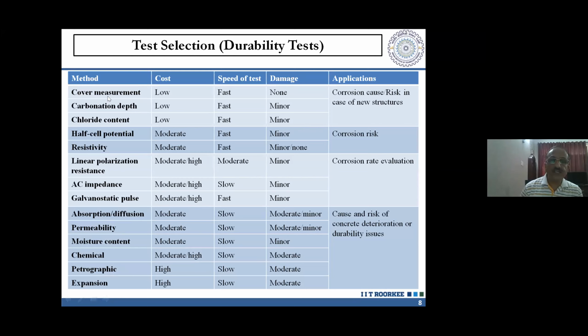But if it's an old structure, cover can be checked to see whether the original cover was sufficient or not, because that will let you know if some problem has been seen. For example, if carbonation or corrosion has been seen, generally you will see that it is at the location where cover was not proper. So cover measurement is required. Carbonation depth is required in order to find the cause of the corrosion. If it is not because of carbonation, chloride content is required to be found. There are different methods. Half cell potential and resistivity are required. These three tests are required to know the cause of the corrosion. These two tests are required in order to check whether the corrosion is active right at the time of testing, and further to demarcate the corroding areas and non-corroding areas, so that you can carry out the rate of corrosion tests on the corroding areas in order to find out the rate of corrosion.